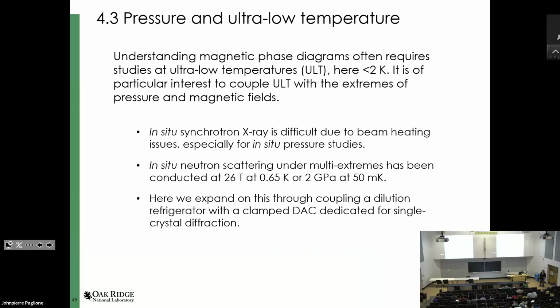Now I just want to use 2 more minutes, if I can, to talk about coupling some of our diamond anvil cells with ultra-low temperatures. Ultra-low temperatures in this context means anything below 2 Kelvin or thereabouts. These are regimes where it is very difficult to do high pressure X-ray scattering, because to get your beam into the diamond anvil cell at the synchrotron, you need a reasonably high energy focused beam, so you have a lot of beam heating. So temperatures are usually limited to 5 Kelvin.